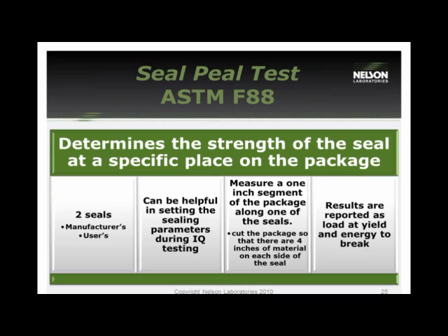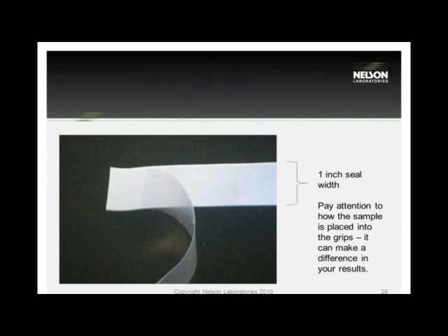The way that the test works is you measure a 1-inch segment of the package along a seal, and then you cut it so there's approximately 4 inches of material that's available on each side so that it's a little bit easy to put into the grips. The results are then reported as load at yield or energy to break. This is a photograph of a seal. It's 1 inch in width, and you need to pay attention to how the sample is placed into the grips. It can make a difference in your results. You don't want to put the stiff material in the top and then for the second sample move it to the bottom because you can get variability.